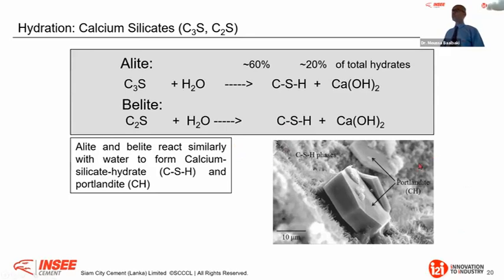And when you look at this scanning electron microscope image, I put it here so that you have a certain idea about the scales, because very often we talk about porosity. What does porosity mean? You see the scales here, we have 10 micron. When we talk about calcium silicate hydrate compared to portlandite, you will see later, this is the weakness of concrete, exactly like in concrete. When we talk concrete, the smallest particle in concrete is cement, about 20 micron, 10 micron. And the biggest particle, the aggregate, is 20,000 micron. Therefore, this big gap will challenge concrete technology to achieve maximum capacity.